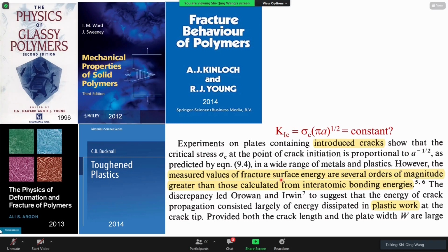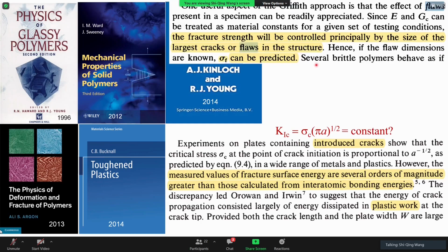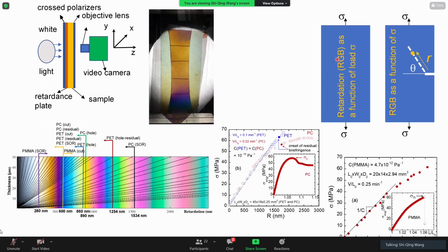On the other hand, how come this relationship works as if fracture mechanics works very well? The past is summarized by this book by Kinloch, basically suggesting the flaws are always the reason for the problem, especially for the fact that the theoretical strength is different from the nominal strength. So we are keen to find out whether the theoretical strength is indeed much larger than the nominal strength. We decided to look at birefringence. It's a beautifully simple technique for this particular problem, because this is really a 2-dimensional problem. All the principal axes are in the plane of your sample, with the third principal axis perpendicular to the sample. So you can validate birefringence as a way to report local information about stress.